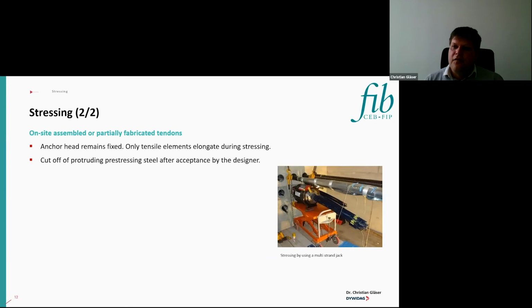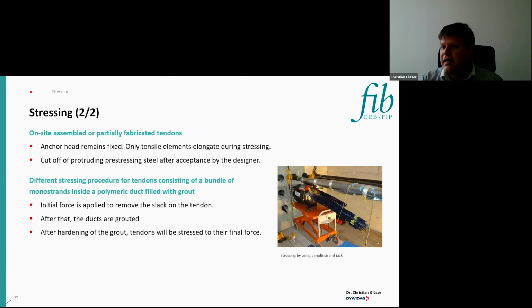For the other types, on-site assembled or partially prefabricated tendons, it's the standard stressing procedure as usually done for internal post-tensioning. So that means the anchor head remains fixed and only the tensile elements elongate during the stressing, and then, usually for strands, these tendons are anchored. Quite an important message is, of course, that cutting off of the protruding pre-stressing steel shall just happen after the designer has accepted the stressing record, because after this it will be difficult to unstress the tendon again.